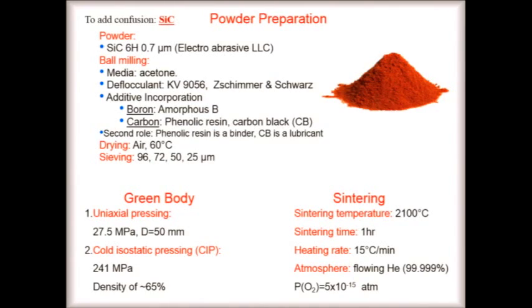I didn't want to look at sintering. It seems to me a little bit complicated. I wanted to compare it to grain growth kinetics, not sintering. So, in order to confuse you further, we prepared this using silicon carbide and not alumina, and made dense silicon carbide samples, which were doped with boron and carbon in the usual way in order to reach full density. By the way, these materials were sintered without pressure, and we got to 94 or 96%. This batch is 94% at 2100 degrees.